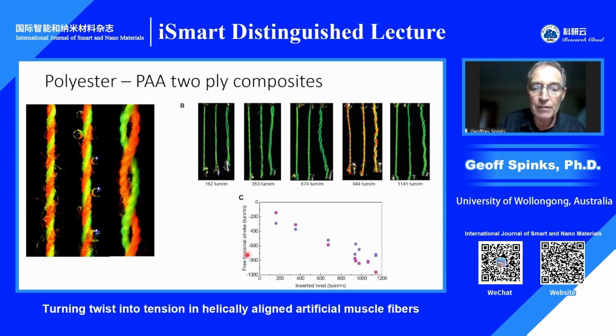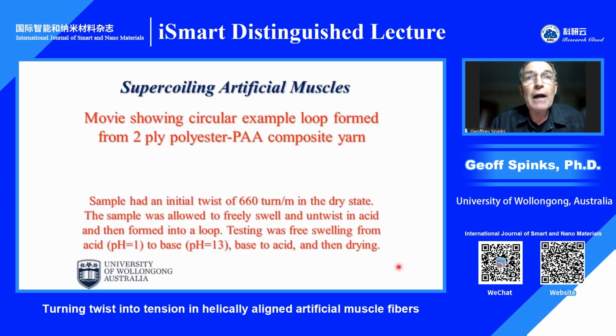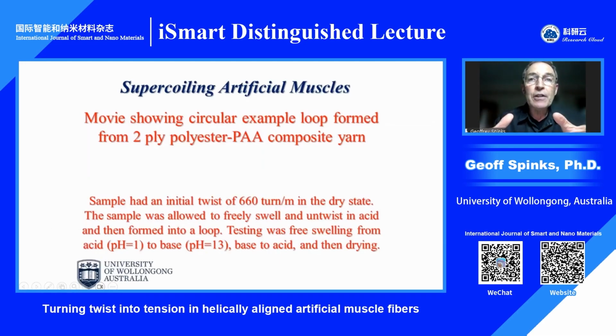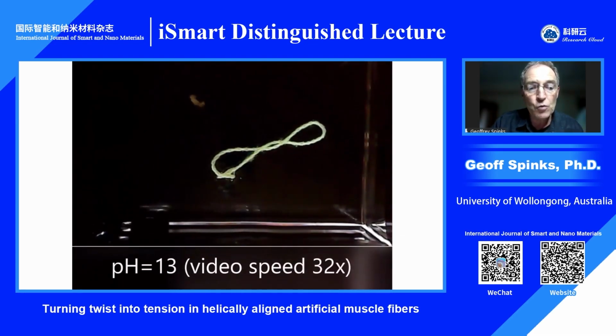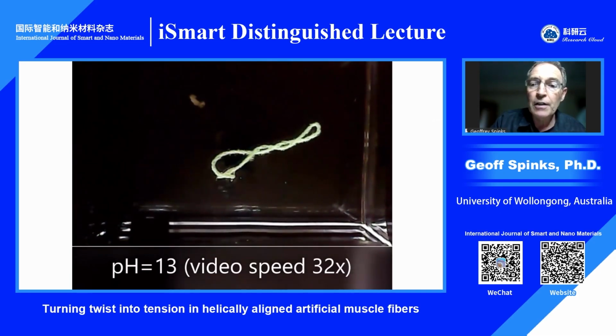And you can see that these are negative numbers indicating untwist. You can see that there's a correlation between the amount of inserted twist and how much rotation occurs during swelling. And in most cases, or in all cases, about 80% of the inserted twist can be removed by swelling. Well, what happens if we now try to encourage supercoiling? The first example took those twisted fibers and did free swelling in acid and then joined the ends to make a loop. So here we see what happens when that loop is now further swollen in base, and you can see it does exactly like the closed circular DNA that we see in the biology textbooks.